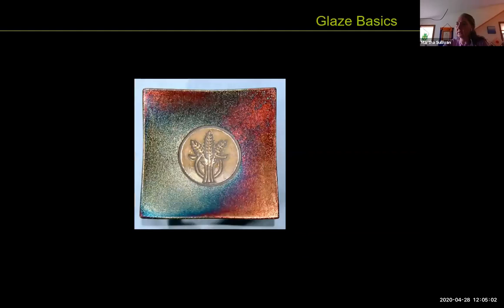Right, and raku is really high in metals, so it's not food safe, and it's also low temperature, so it's very porous. But here, there's a gold medallion in the center, which is a gold-based glaze, and then that outside is a copper-based glaze. And even though some of it is very copper and some of it is very green or very red, it's all one glaze. And depending on where it is in the fire, changes where those fumes change the color. So although you might know it's going to be a rainbow, you have no idea where the rainbow colors are going to show up.